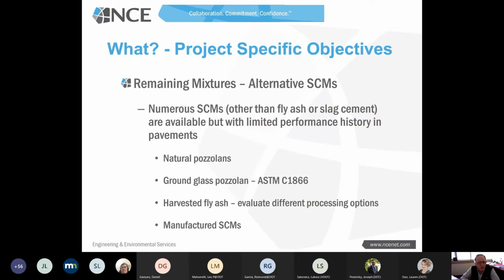And some of the things that we're going to be evaluating are natural pozzolans. Natural pozzolans are materials that occur naturally, as the name implies, but they have the same chemical or physical benefits that we see from fly ash. These are primarily available in the western states, and so we have two cells dedicated to looking at natural pozzolans. Ground glass is a relatively new material that's been developed, or has recently had an ASTM specification developed for it. It's basically consumer glass that has been ground extremely fine to cement fineness, and then it can be used as a pozzolan. It's extremely pozzolanic, a very, very high performing material. And we will be evaluating that in the one cell dedicated to ground glass.